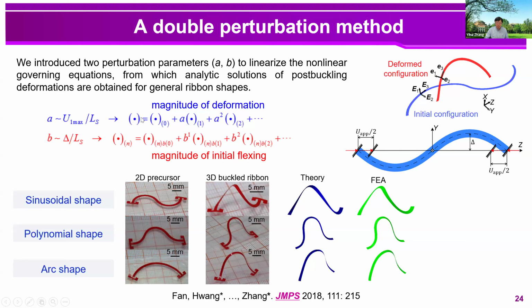And one of the parameters is related to the magnitude of the out-of-plane deformation, and the other is related to the magnitude of the initial flexing level of the 2D precursor. So if you look at the results on the bottom, you will see that the analytical solutions agree very well with our experimental results and also FEA results.